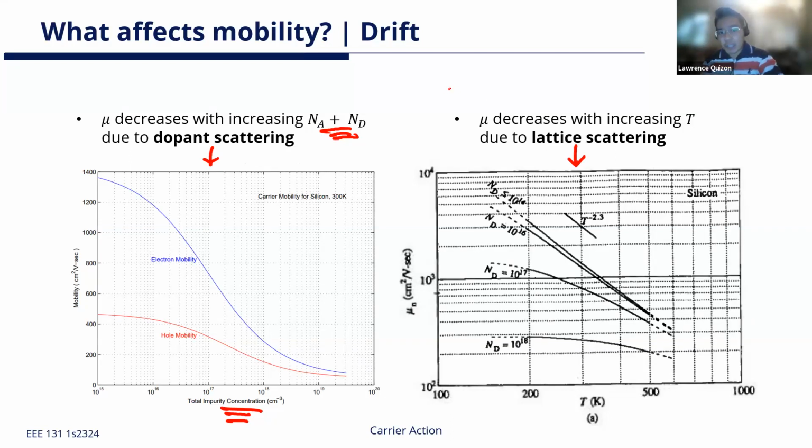As I said earlier, part of the reason why the electron starts bouncing around with everything is because of temperature moving it randomly, right? As you increase the temperature, the silicon actually starts vibrating as well, no? So then it's more likely to bump into silicon as you increase the temperature, no? So increasing temperature also decreases the mobility.